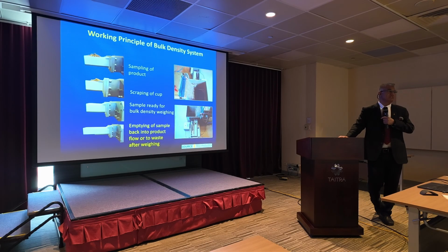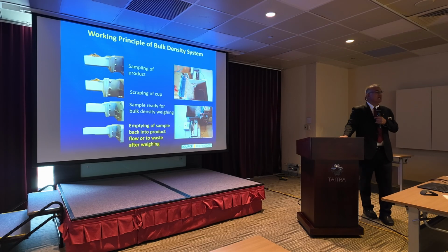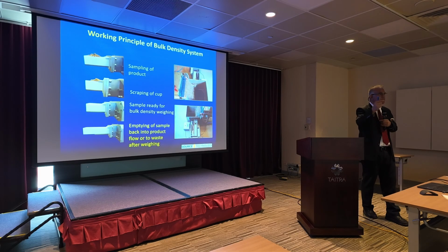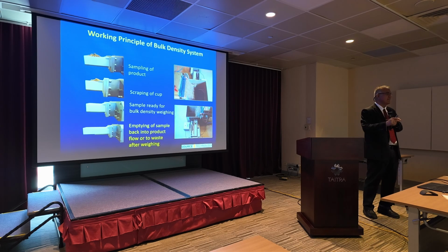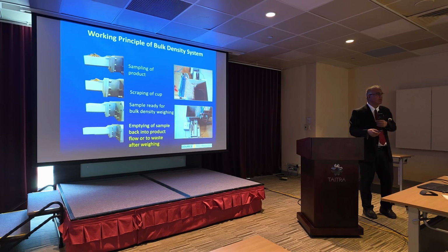You want to make sure your density is right. You don't want to make all the product for one day and then realize that your product density is off, and then you have to rework it. This gives you real time, every 15 seconds, the display that your density is off. Therefore, the dryer will talk to the extruder. The extruder operator will know my density is off, increase the pressure, increase the temperature, increase the moisture to adjust your density. Because you have to communicate in real time. You don't want to make your product and then waste it. That doesn't work that way, because you want to make sure that they are working properly.